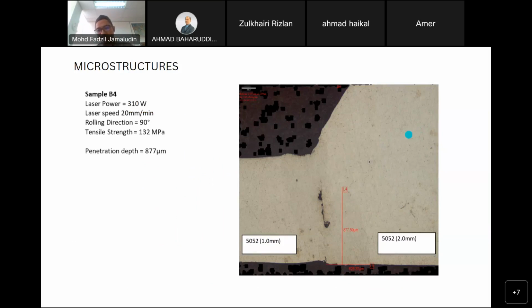I'm not sure you can see clearly here, but you can see the penetration depth of the laser. It's around 800 micron, one side in this side and one side in this side. So we can see that in some cases, because of the nature of the beam, a very fine beam, any minor misalignment shows. It is very difficult to have it aligned for double-sided welding unless you have some automated system.